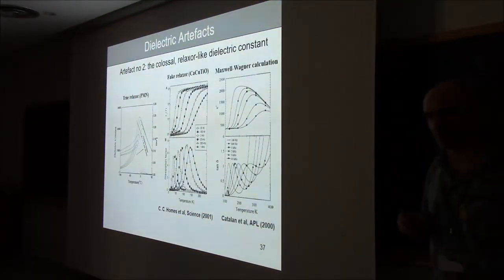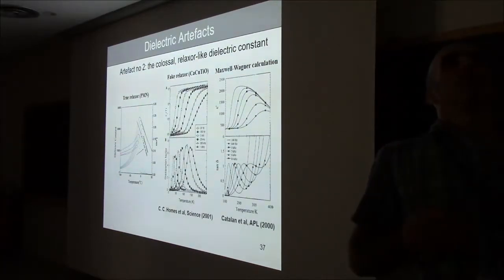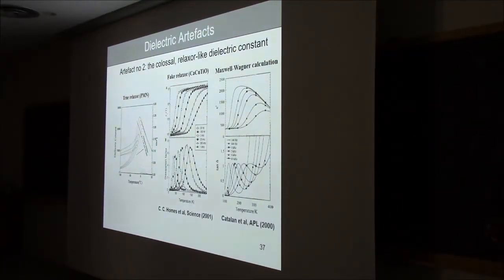This consideration about the velocity of the measurement means that ferroelectric switching is very rapid. Yes. And what is the typical time scale for very rapid? Well, at room temperature, the thing is, switching itself has very complicated physics, because even though an individual dipole can switch in the gigahertz regime, switching normally proceeds by nucleation of an antiparallel domain that has to grow and then expand. And that growth and expansion depends on temperature. So in fact, at low temperatures, it can be quite slow, but at room temperature, this happens within microseconds.